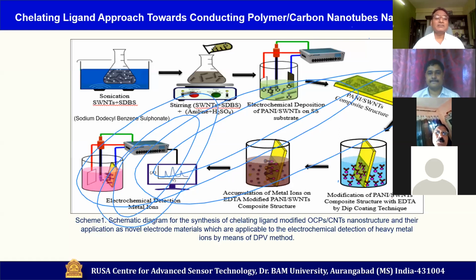What we are doing, you see here, we are using SDBS as a surfactant. With single walled carbon nanotube, we are doing sonication so that you can have the debundling of the CNTs. And then we are adding aniline and dopant, and we are doing stirring of that, right? Once we have the homogeneous solution, then we are moving ahead and doing electrochemical synthesis of this on the desired substrate. It could be platinum, it could be stainless steel, or it could be whatever conducting electrode.